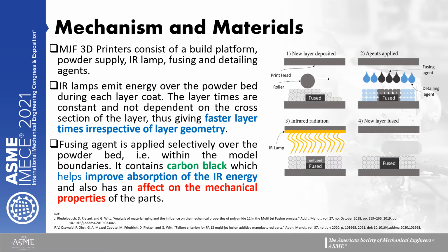A brief idea about the working mechanism of multi-jet fusion 3D printing is shown in this slide. A multi-jet fusion 3D printer consists of a build platform, powder supply, infrared lamp, fusing, and detailing agents. Infrared lamps emit energy over the powder bed during each layer coat. The layer times are constant and not dependent on the cross section of the layer, thus giving faster layer times irrespective of layer geometry.